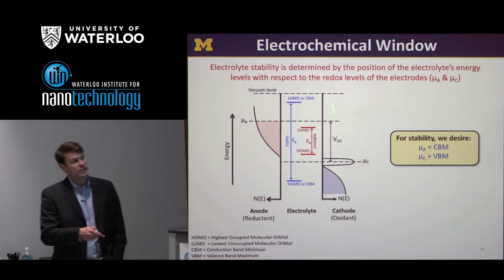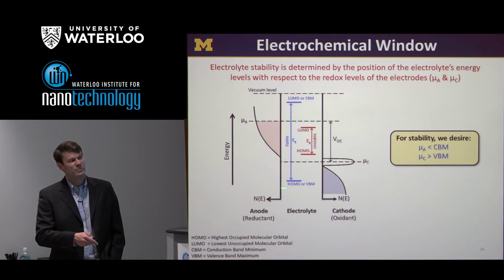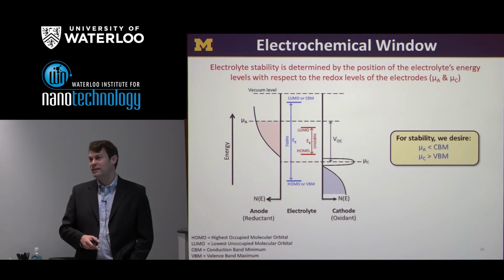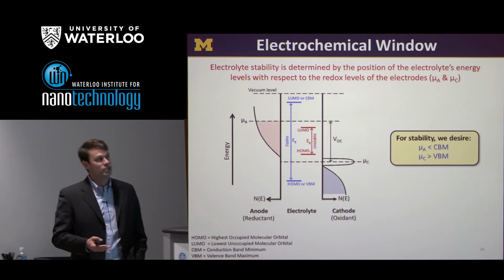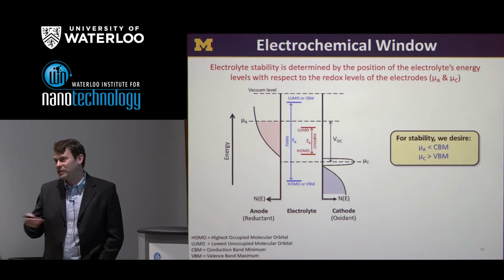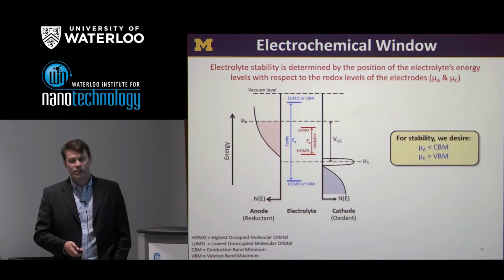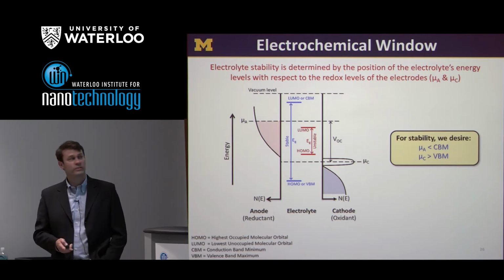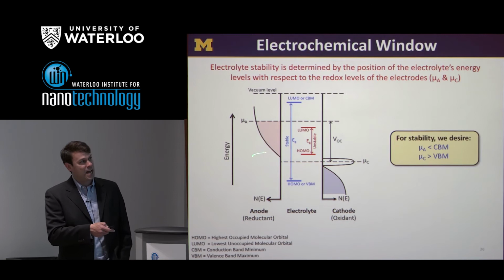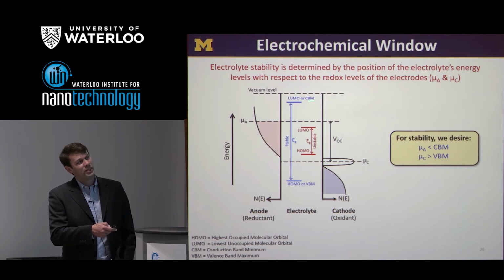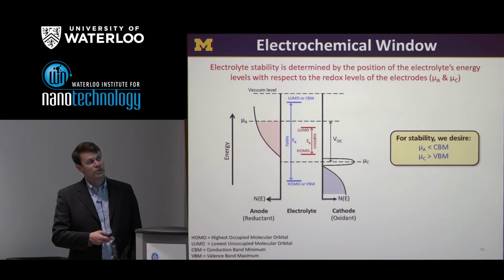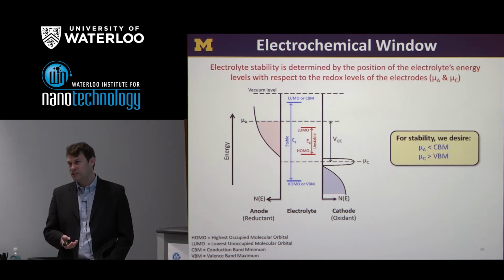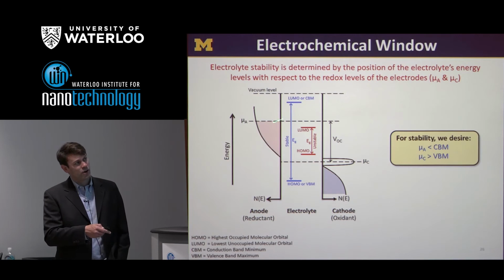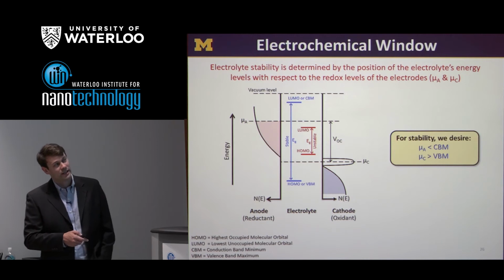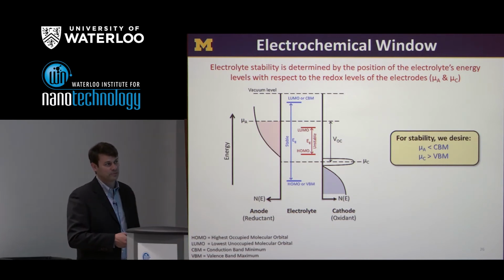And I should say that in liquid systems, it's now rather routine to estimate the positions of the HOMO and LUMO and assess whether a given component of your electrolyte is suitable for use in a battery of a given operating voltage. Not much has been done in solids to get this same sort of information. We can get things like the band gap, which would be here Eg, between the conduction band minimum and the valence band maximum, but it would also be really helpful to know the absolute positions of these band edges. So where does this blue line fall, for example, with respect to these potentials, which we get, as I'll show you, by going through an analysis of using the vacuum level.